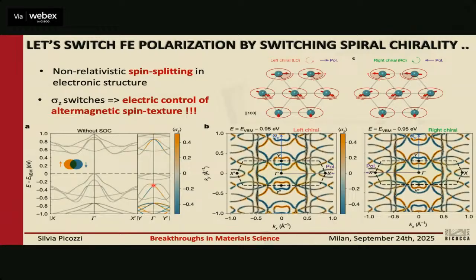So is there any similarity with Rashba-induced spin splitting? That's a very good question. This is non-relativistic, you mentioned? Yeah, it's non-relativistic. So I'm a fan of spin-orbit coupling, and I work on every aspect of spin-orbit coupling. But the catch of altermagnetism and the way they sell it is that it's non-relativistic. Right? And this is the non-relativistic band structure. So if I see a spin splitting here, it cannot come from spin-orbit coupling. We thought, okay, it's iodine, then spin-orbit coupling will change the situation, but actually it doesn't, right? You have small modification.